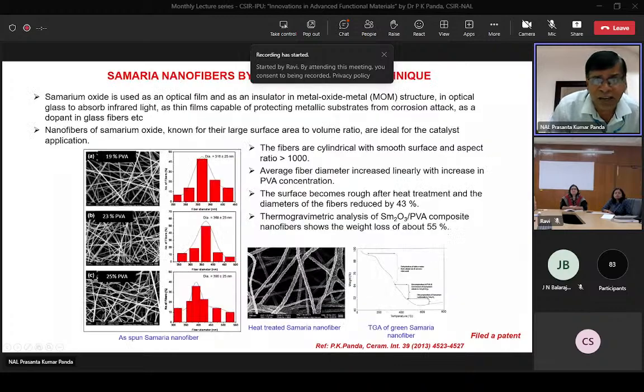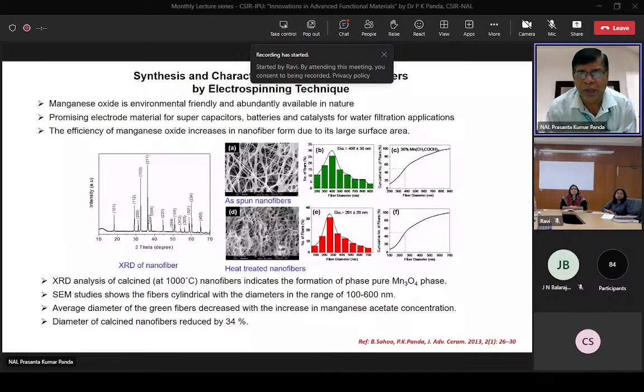Similarly, this Samaria nanofiber was prepared by the electrospinning technique, and a patent was also filed. The publication is now in Ceramics International. It is a similar procedure, only you change the polymer precursors and processing conditions, and accordingly you have to change the concentrations. Their diameter was measured, and their diameter after calcination was also measured. All those details are available in the published literature. Similarly, manganese tetroxide was also prepared by the electrospinning technique, and this is also in a publication.